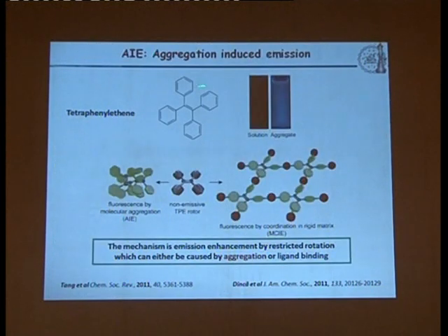So this is another molecule which recently came up, called tetraphenylethylene, which is called an AIE molecule. This has come from Tang. Tang has introduced this molecule. As I mentioned in the previous slides, this particular molecule is non-fluorescent in solution when it exists in a free state because of the rotation around this double bond. But as soon as it goes to an aggregated state, or if we can restrict the rotation of this molecule, it is highly fluorescent. So that is why it is called an AIE molecule, aggregation-induced emission molecule.